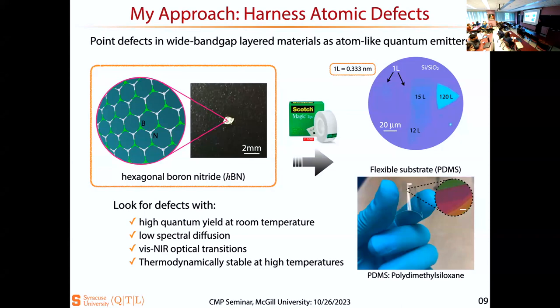In my research on boron nitride, I have worked with both single crystals, which you buy from the company, and boron nitride we grew ourselves using CVD, chemical vapor deposition. In our previous group, we had both the natural crystal from the company and the CVD growth sample. I worked with both of them, but from my experience, the quality of the single photon source is much better when we get it from the company.